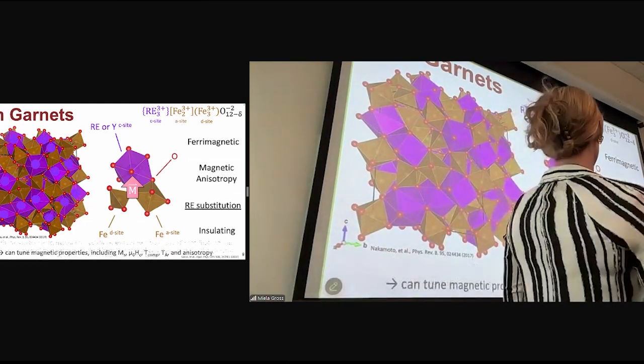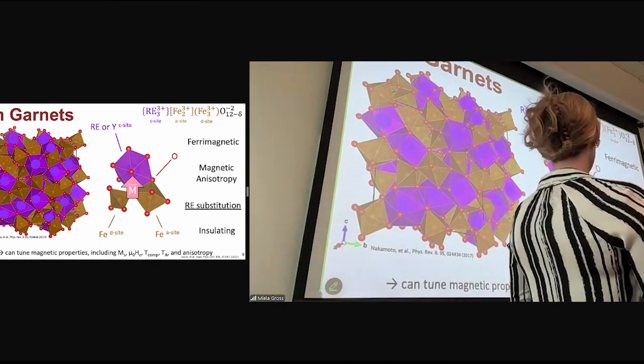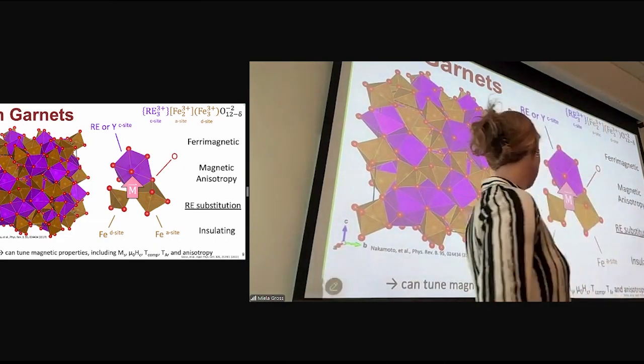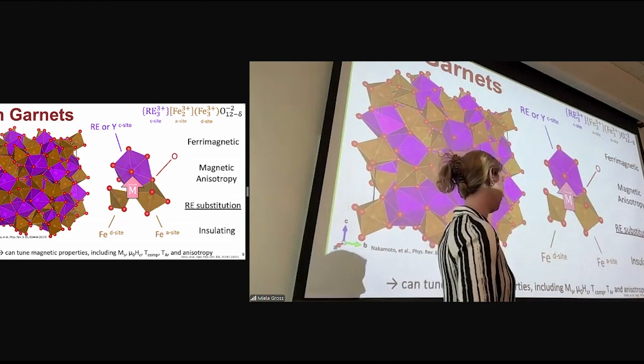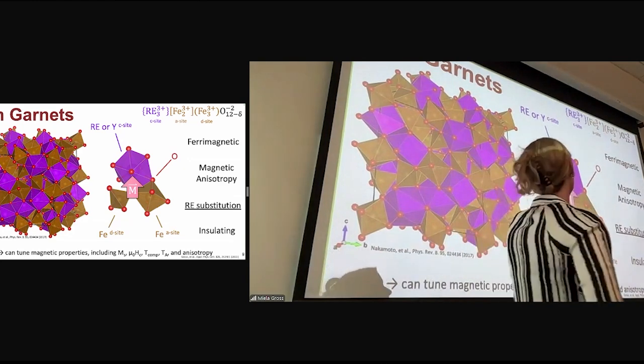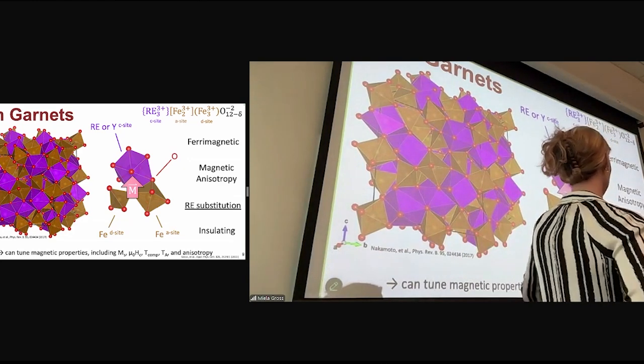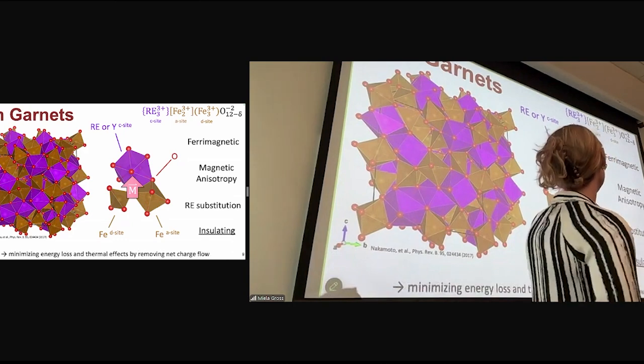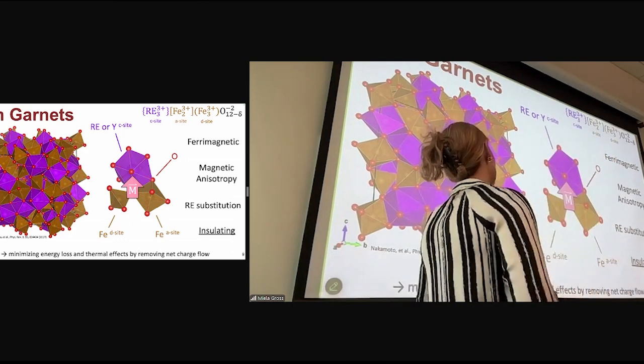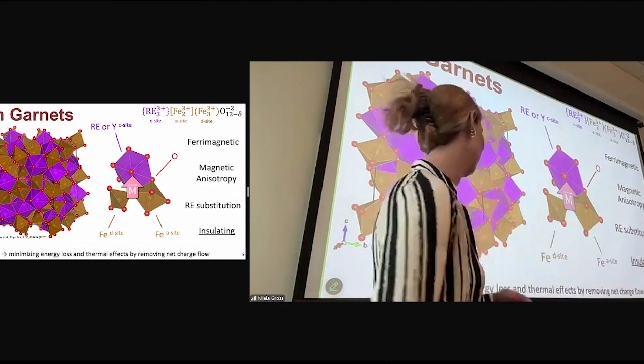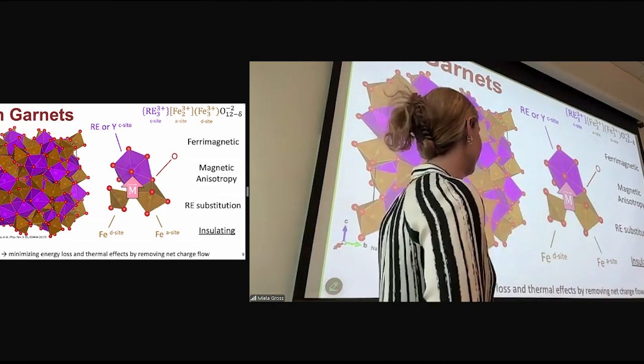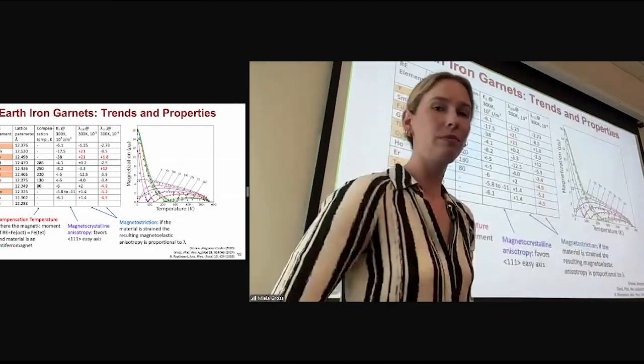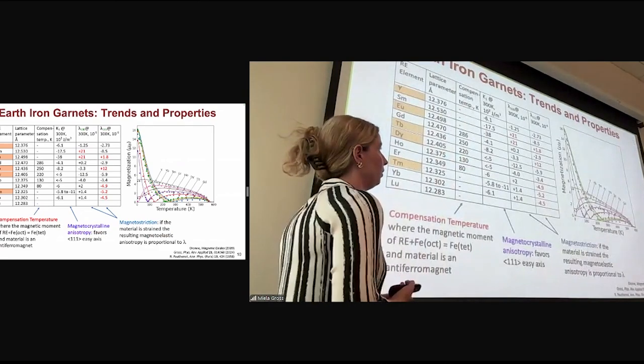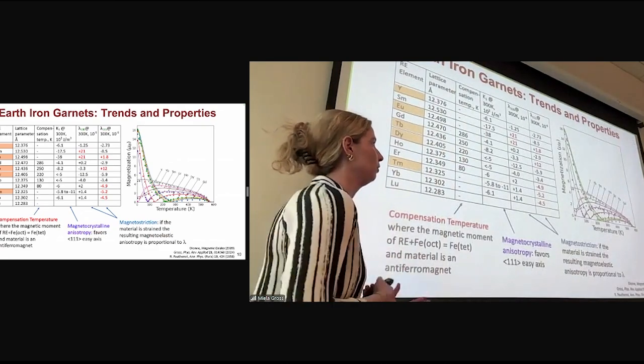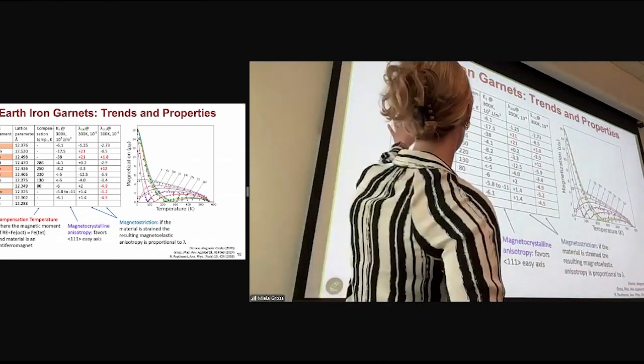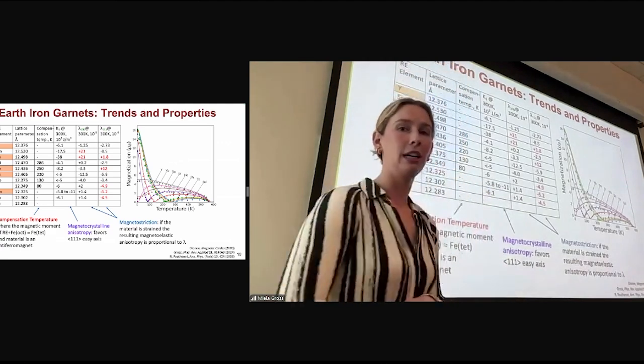And that ion substitution happens in this rare earth site here. But this ion substitution also allows us to tune other magnetic properties, including saturation magnetization, coercivity, and compensation temperature as well. And lastly, these garnets are insulating, which means there are no conducting electrons to worry about energy loss or thermal effects. So this slide here shows all the different properties that you can tune by basically putting different rare earths in those C sites of iron garnets.